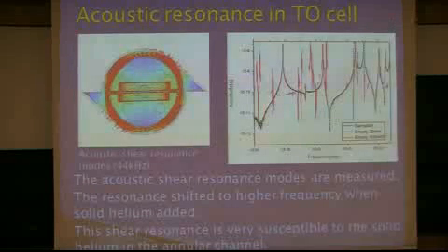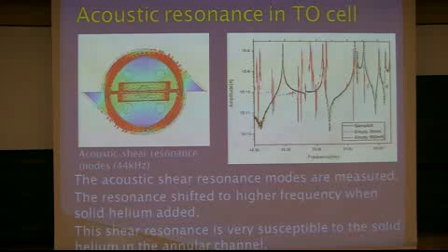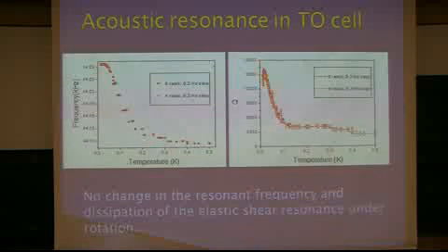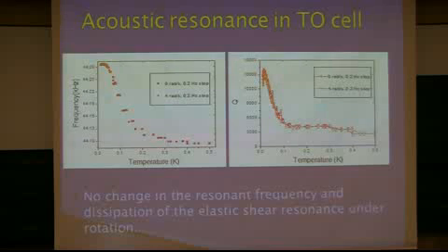No change. However, I want to be really careful. I'm a really careful experimentalist. Maybe since we measure the shear modulus at the center, the rotation effect is too small to have any observable change. That's why I generated acoustic resonance in the torsion cells. This acoustic shear resonance is also very sensitive to changes in elastic property, and it is very sensitive to the solid helium in the annular channel. We did the experiment again from 0 rotation and increased the rotation speed up to 4 radians per second. As you can see, this is just a single curve, no change, as we expected, since 4 radians per second is too small to cause any change in the elastic modulus.